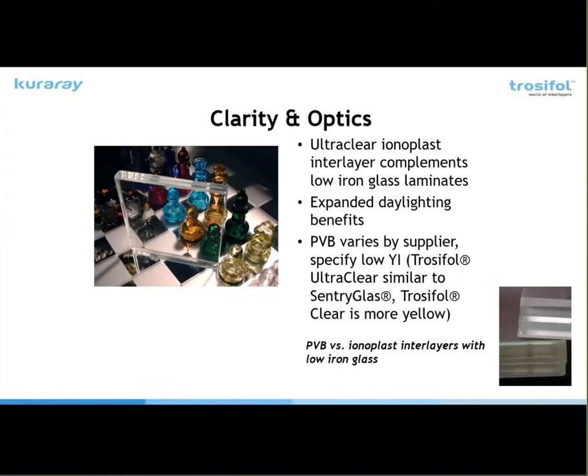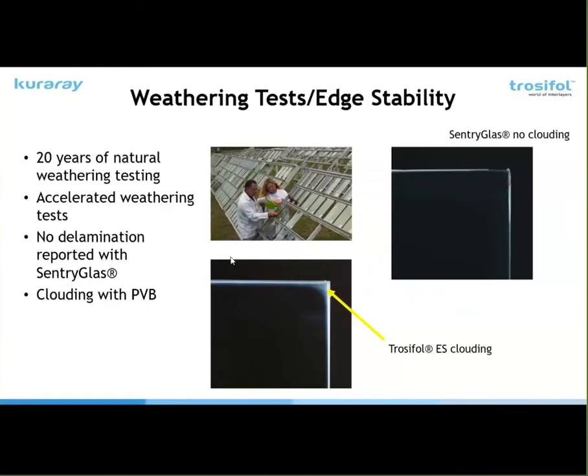It also occurs when you have a butt glaze system. My colleague Ron, who is on the call, lives in Florida and got some of these pictures in Orlando at the airport, and you can see what happens in a butt glaze system. It's very good as far as water resistance. As far as moisture is concerned, you get some ingress, and then you start seeing some delamination. Here it's pretty horrific where they obviously didn't seal the point very well, and you see this crystallizing appearance.